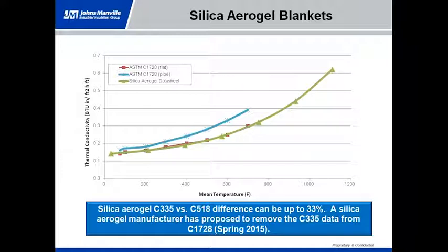Now here's the plot for flat data, and maybe kind of a giveaway, this was actually from a silica aerogel manufacturer's data sheet. If you look at this plot, you can see that it goes up to 1100 degrees, which tells us it's flat testing. And notice that it lays right on top of the ASTM C1728 flat testing, the C518 testing. So looking at this, I think it's safe to say that the ASTM and the data sheet are in agreement as far as what the requirements are, and below that is the C1728 pipe line. The challenge, though, is that you can see there's a difference between the two, C335 and C518. On a previous slide, we saw that it can be 15 to 30%. In this case, within the silica aerogel standard, it's a 33% difference.